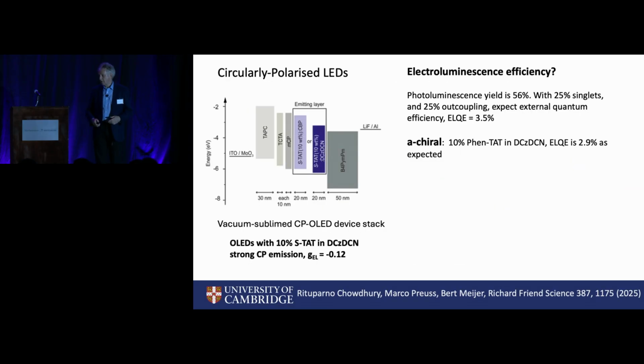We've got the chiral structure, and we've got a thin film, which is chiral, and we can now put that into the middle of the sort of stack that is used for a standard organic LED. So we were happy to do that. We could get quite good circular polarization of the electroluminescence, which is good. But there was a surprise.